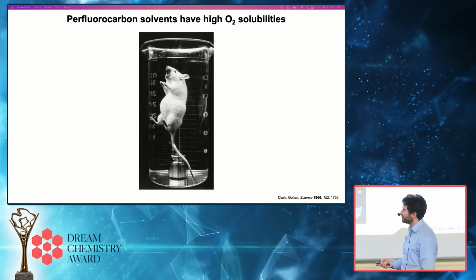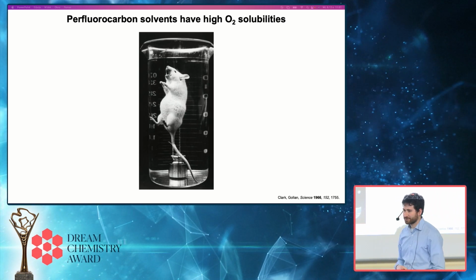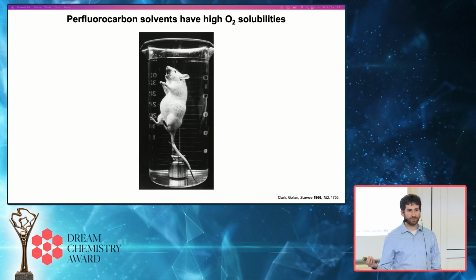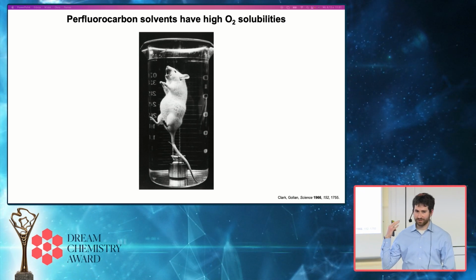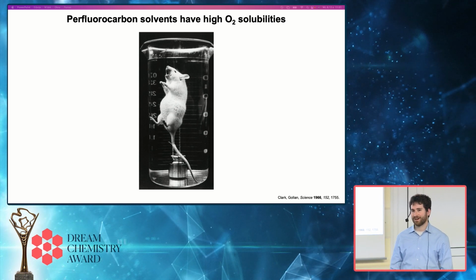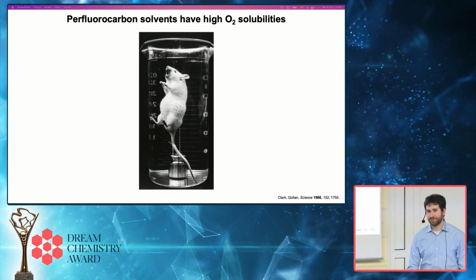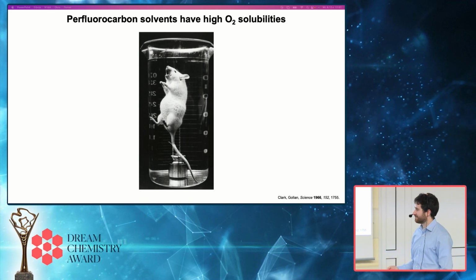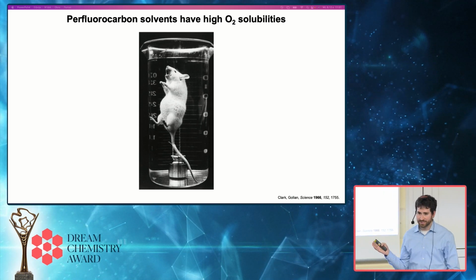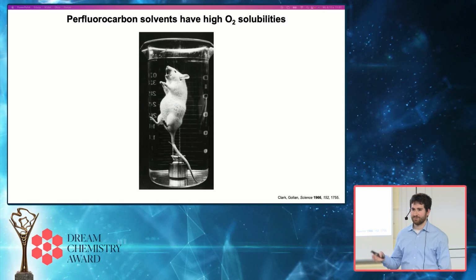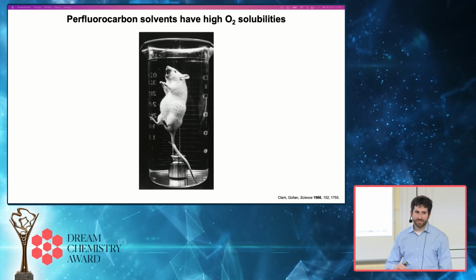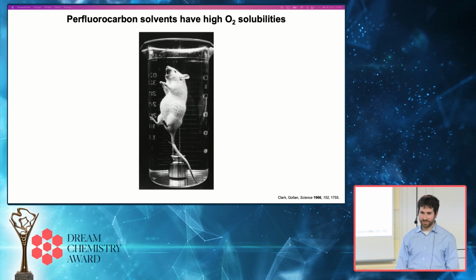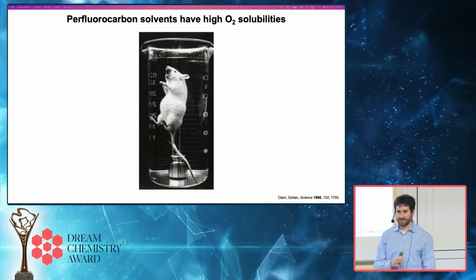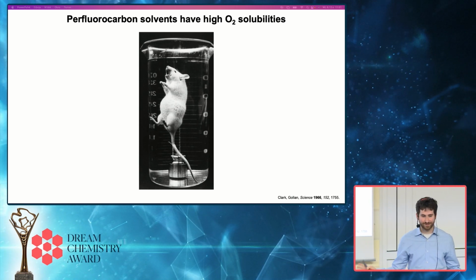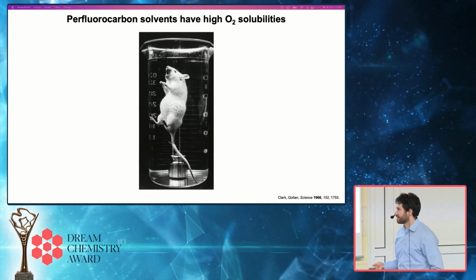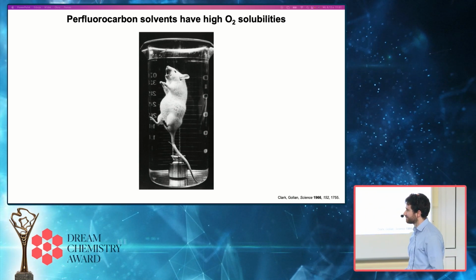And so if you just take a pure perfluorocarbon liquid, this is, I think, perfluorodecane, you can actually submerge a mouse and its lungs will fill with liquid, but it won't drown because there's enough oxygen that's intrinsically present in the perfluorocarbon liquid to keep the mouse alive. So this is a famous experiment from the 1960s with a mouse that was ventilated with liquid perfluorocarbon solvent, just equilibrated with air through passive diffusion, that stayed alive for 4 hours and remained alive even when outside the perfluorocarbon liquid. So this goes to show how much oxygen is there in this kind of liquid compared to water.